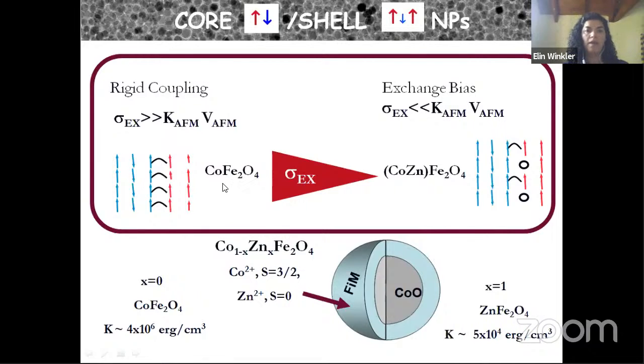So if we fabricate core-shell nanoparticles where the core is always cobalt monoxide, but we systematically change the shell, replacing the cobalt by zinc, we can move systematically in that way, reducing the exchange interaction, the coupling at the interface, while the anisotropy energy of the antiferromagnetic phase remains constant.